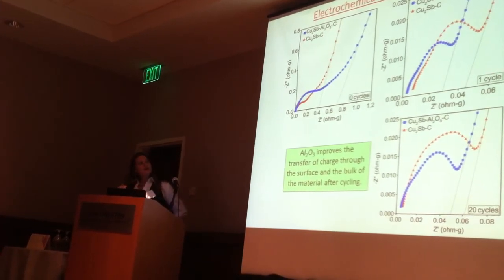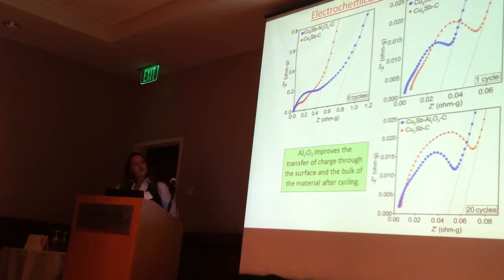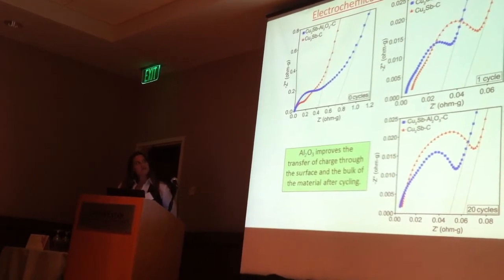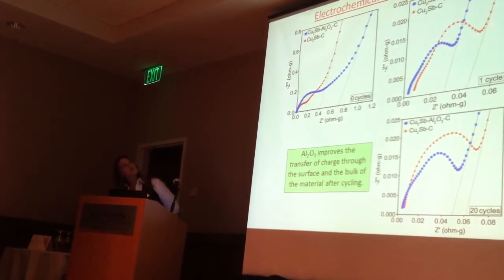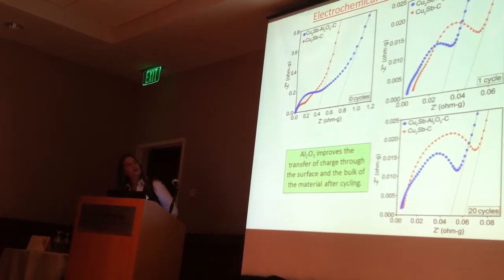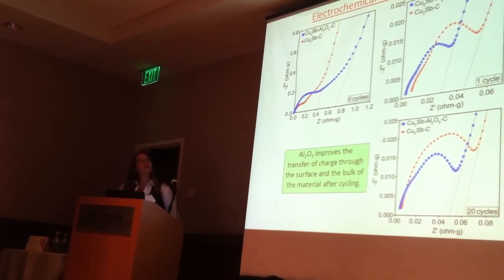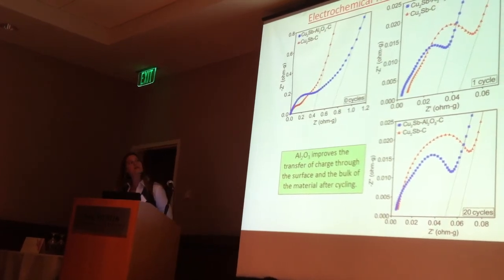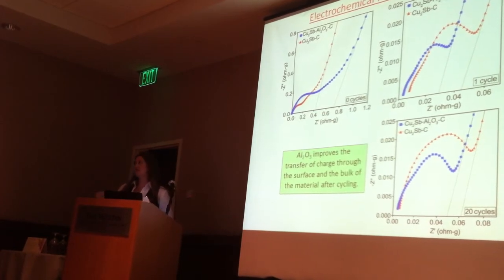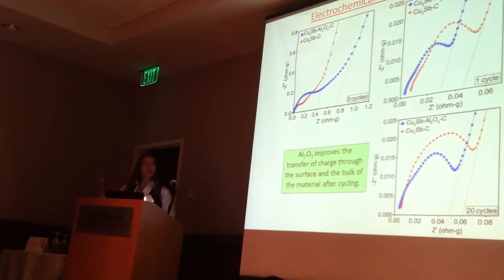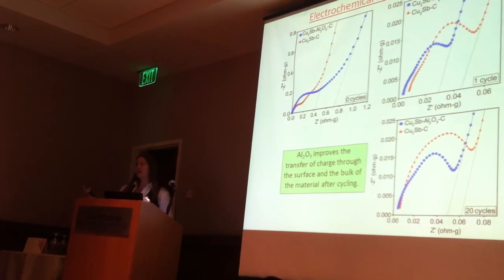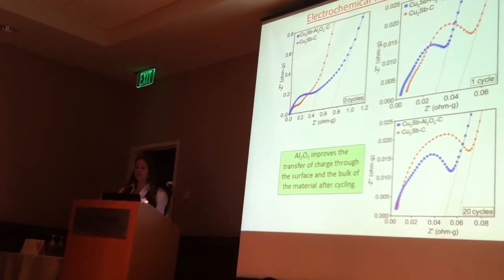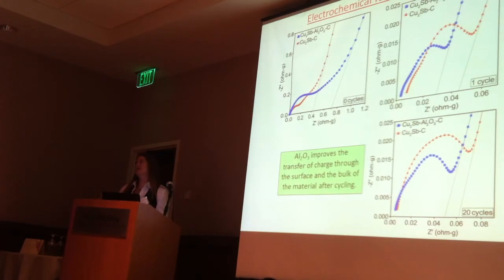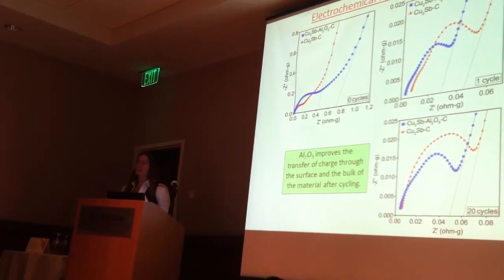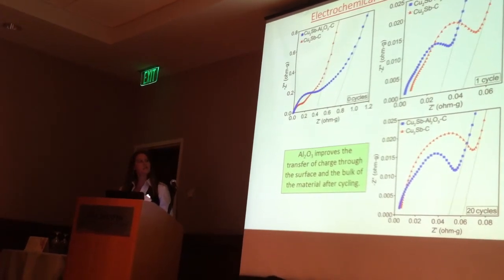So after you cycle this material even 1 or 20 times, you can see that compared to, okay, so the blue is with aluminum oxide, the red is without aluminum oxide, and you can see that in all the frequency ranges, when you have aluminum oxide in your material, it is reducing the resistance to charge transfer. So big clue number 1 is aluminum oxide is improving the transfer of charge in this material, and that's obviously impacting the reversibility of the reaction that it has with lithium.